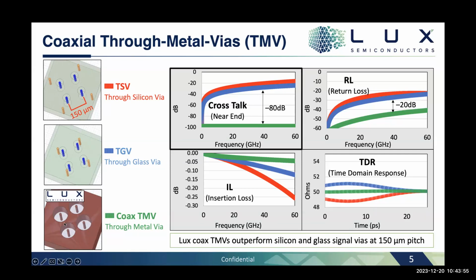Now you can actually carve out this metal in between as well to continue to push these signal pins closer and closer, removing that metal shield. And so your crosstalk is going to go up significantly when you do that. However, the natural state here is coaxial, and so you just don't get any crosstalk through that grounded metal shield. The other big difference is TDR. With 50 ohm via design, it's very simple to do that with the TMV. You just change the ID or OD of your TMV. With this, it's like laying out ground pins around signal pins. We've talked to multiple designers, and I guess it's quite a challenge to tune your vias in a way that also works with the layout that you want for all your vias.